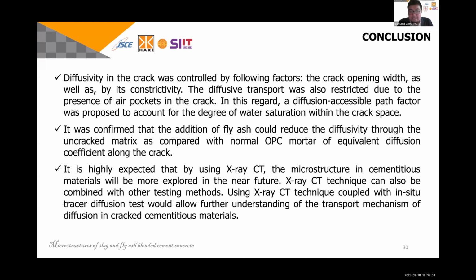You may check the change in the crack due to high temperature exposure and recurring, and then you may apply any condition. And the final, using the X-ray CT coupled with in situ tracer diffusion test would allow further understanding of the transport mechanism of the diffusion in the cracked cementitious material.